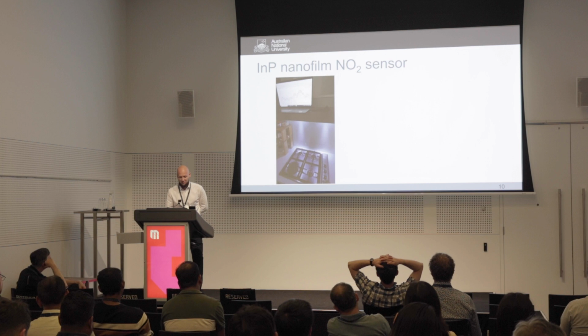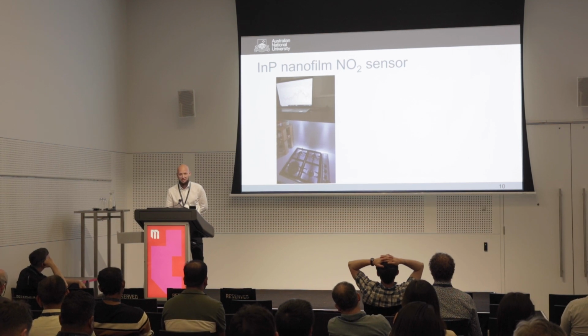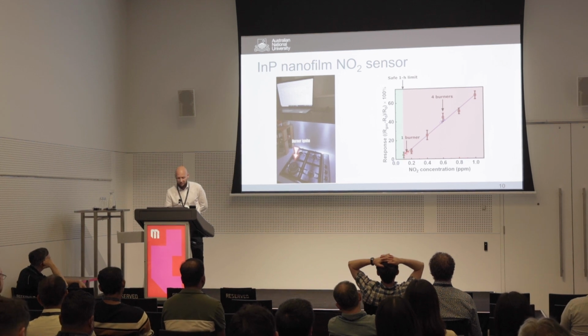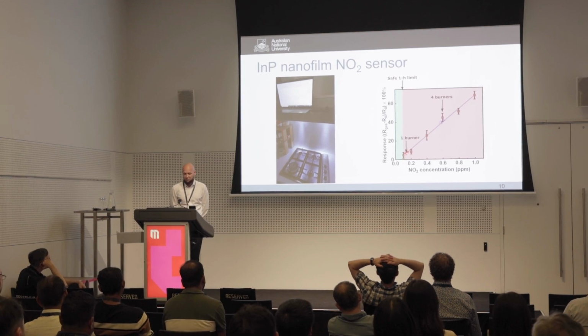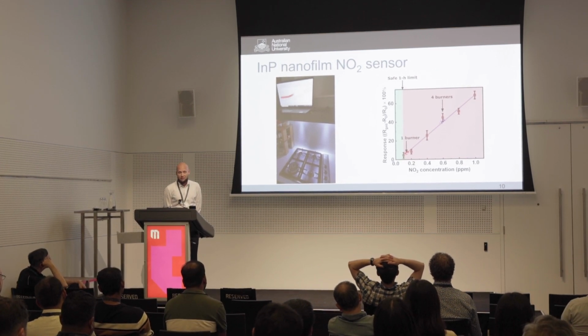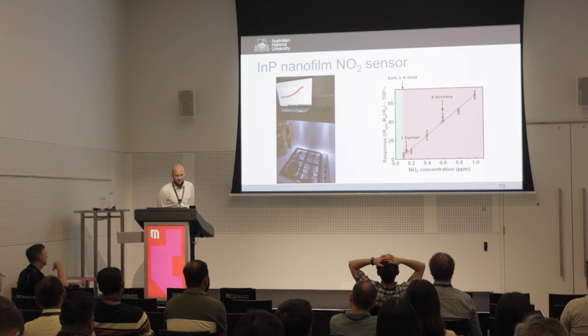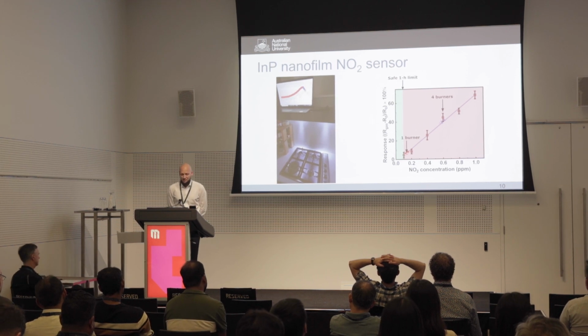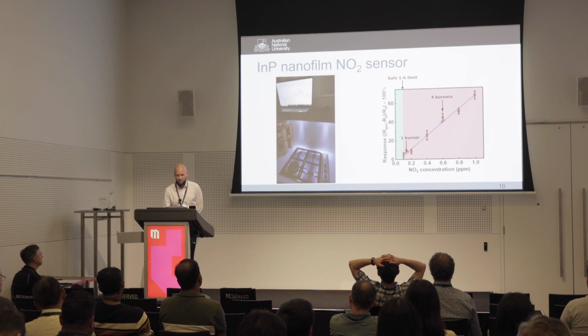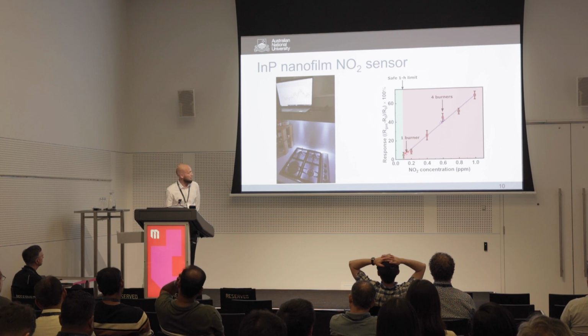And some of you may be wondering just what does this peak here correspond to? Well, it corresponds to about 150 ppb NO2 level, which is actually already above the safe limit considered for 1 hour exposure. So if you spend 1 hour in a small kitchen or a poorly ventilated kitchen, you will be exposed to harmful levels of NO2. And the situation is of course worse if you have more burners on.